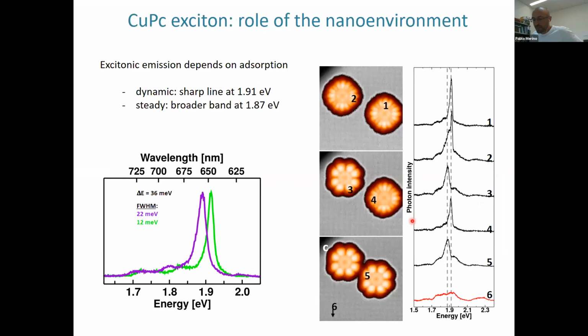But the important part of this system is that in this case, the 2 molecules do emit at different wavelengths, okay? The molecules sitting on chlorine and the molecules sitting on sodium emit with a 36 millielectron volt difference. And actually the dynamic shows a sharp line at 1.91 electron volts, while the steady is redshifted and is broader.